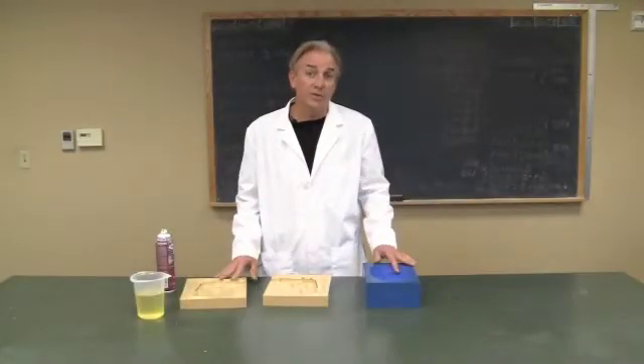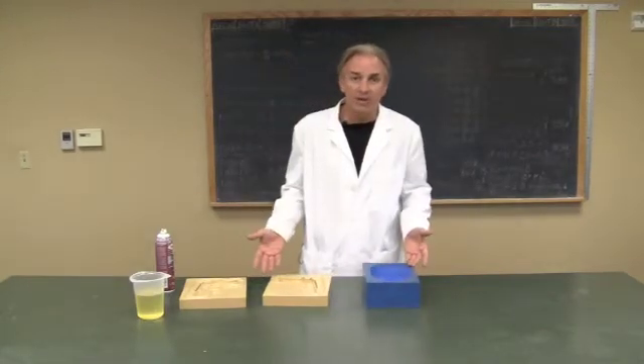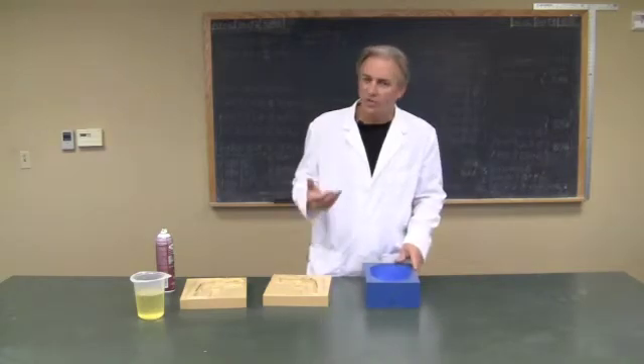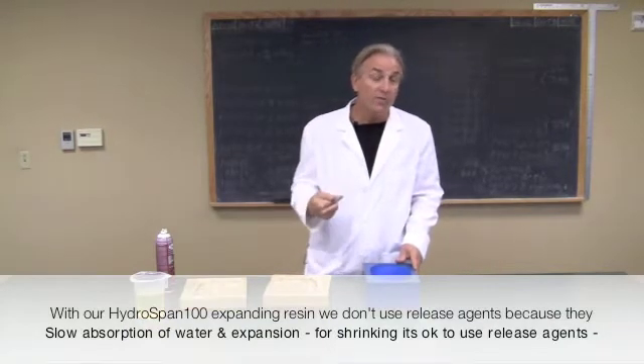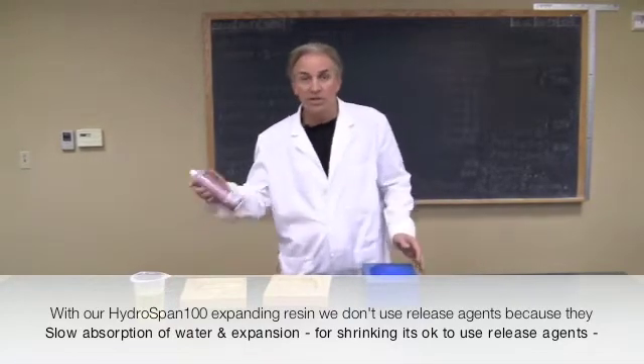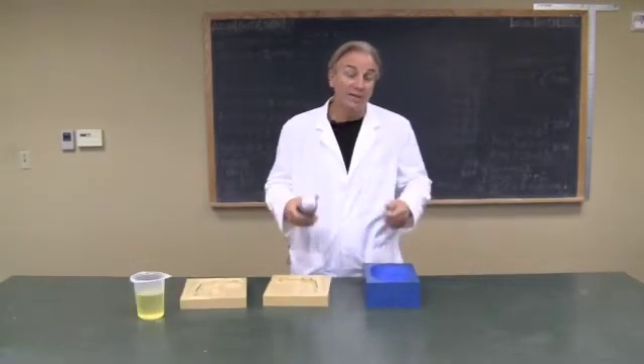To demonstrate the ability of HydroSpan 400, we've chosen some molds to work with. These molds were made of polyurethane, not silicone. HydroSpan 100, as we talked about in earlier videos, requires a silicone mold because it's going to be absorbing the water. However, with HydroSpan 400, you can use polyurethane molds with silicone release to get the same effect because the water is going to be leaving the part.